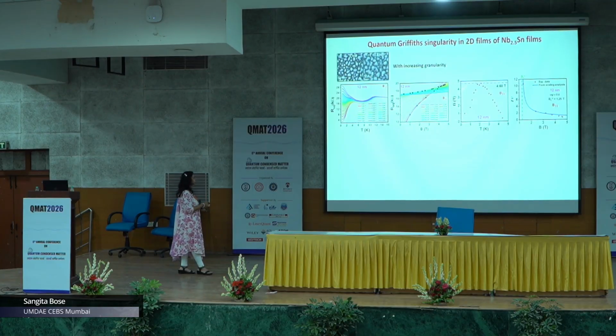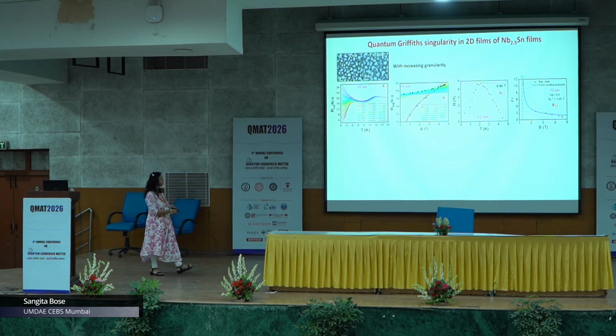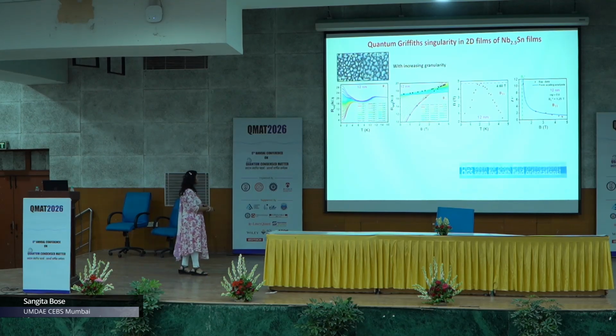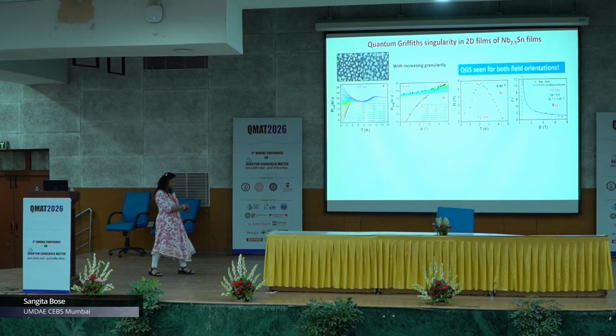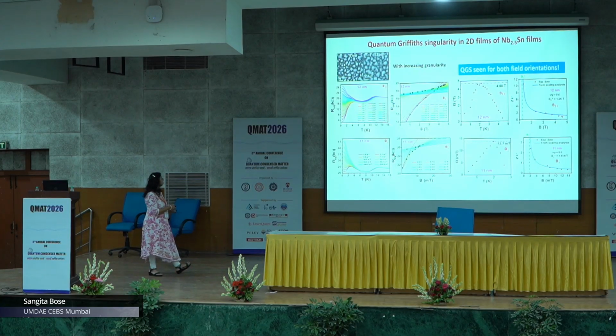Now, again the same scaling analysis gives this anomalous behavior very clearly, this non-monotonic behavior of the variation of the magnetic field with temperature, and you see this divergence of the critical exponent. Further on, basically you see QGS in both the field orientations. Now, if you go to even lower thicknesses, you see that this transition at the quantum critical point is shifted to extremely low fields. So, it was 4.68 Tesla.